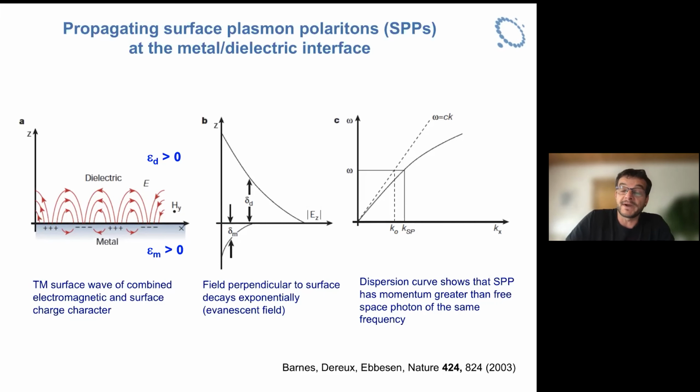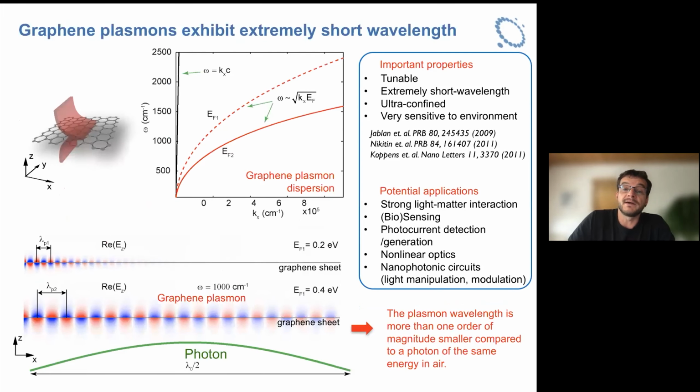This is very classic, but with the emergence of graphene, these plasmonic concepts were transferred to 2D materials. And here graphene is an extreme example. It's a monolayer, a conductive sheet. If it is doped, we have a negative permittivity, and we can excite in these single monolayers of graphene plasmon polaritons, so it's important that the graphene is doped.